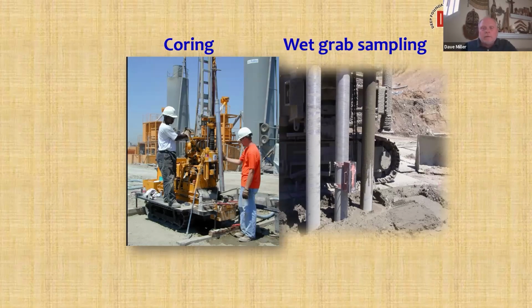Anyway, so there's wet grab sampling to make specifications. You test permeability, typically at 28 days. Most specs are written around an unconfined compression test at 28 days. And then a lot of specs require you to core it. Sometimes that's not really practical depending on the stratigraphy. And then the backup option in my mind is televideo and geologging. Sometimes it's required. And then if you have a permeability test, you look at ways to test that. Many times they specify in-situ tests like falling head or pump tests. Other times they can do it from wet grab samples.